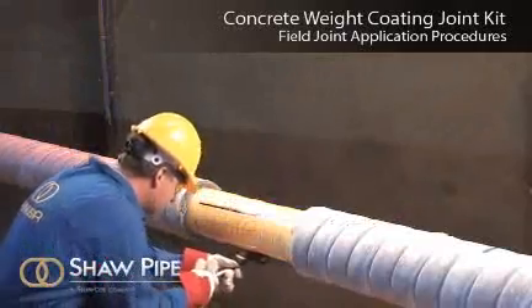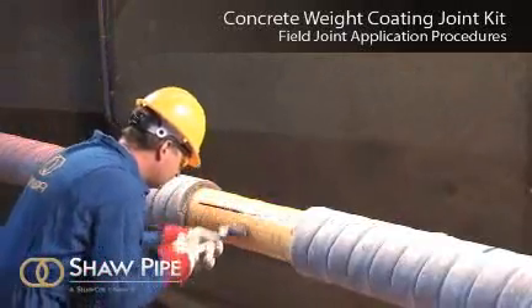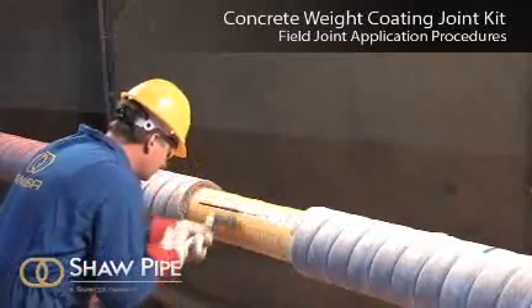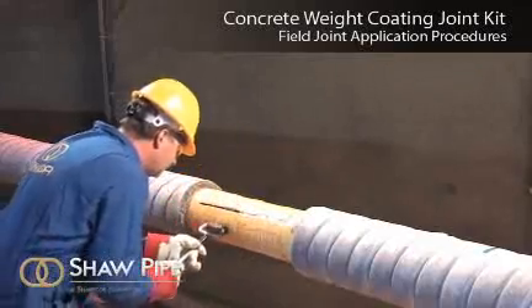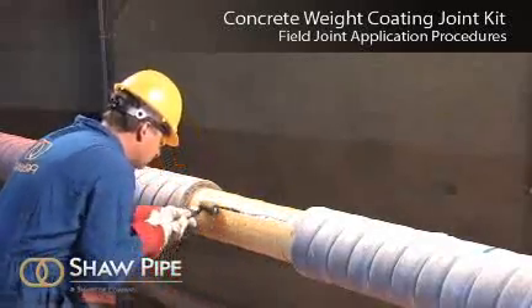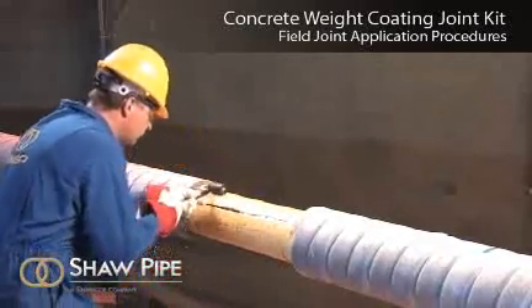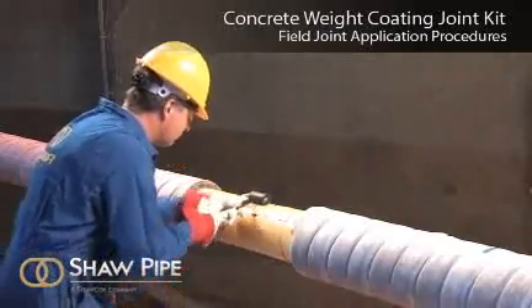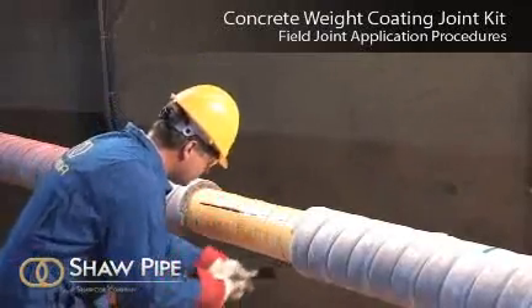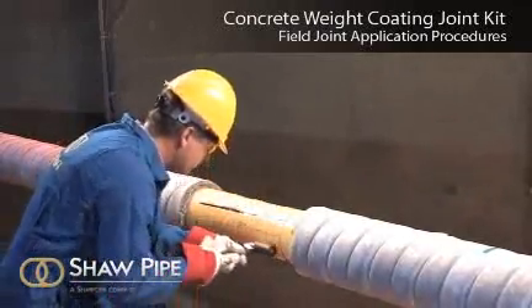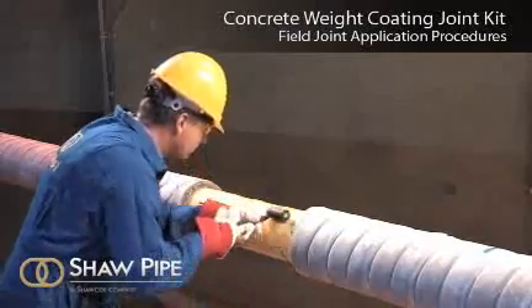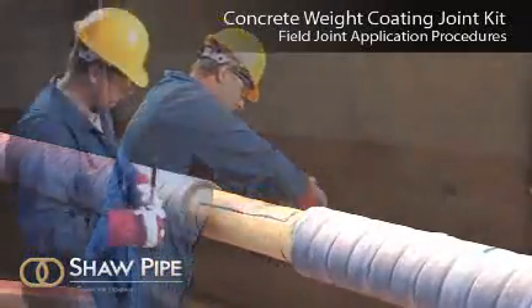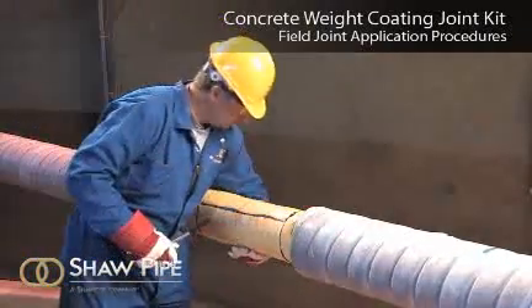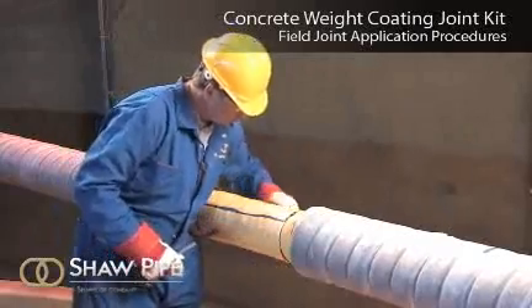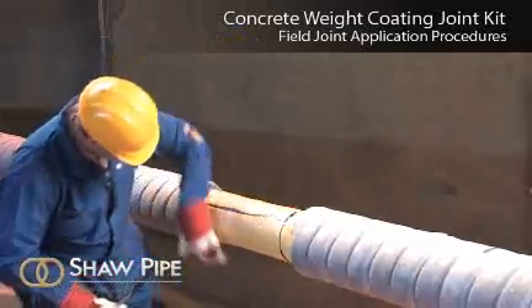While the sleeve is still hot and soft, use a hand roller to gently roll the sleeve surface and push any trapped air up and out of the sleeve. If necessary, reheat to roll out air. Visually inspect the installed sleeve and make sure that the sleeve is in full contact with the steel joint, that the adhesive flowed beyond both sleeve edges, and that no cracks or holes are in the sleeve backing.